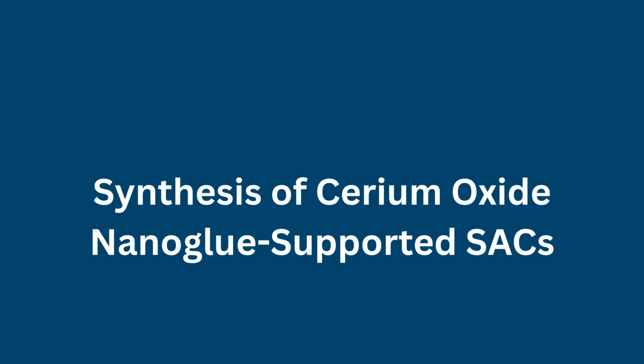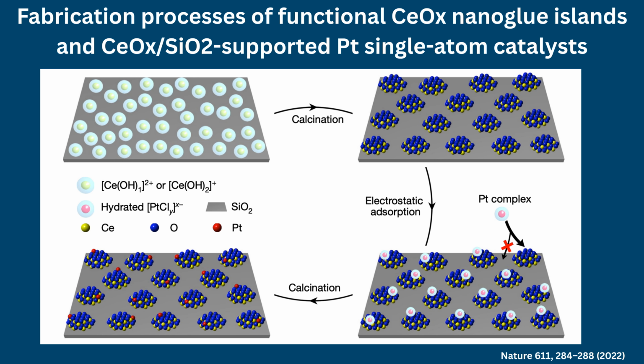Synthesis of cerium oxide nanoglue-supported SACs. The synthesis involves a scalable aqueous phase method based on strong electrostatic adsorption. Negatively charged SiO2 surfaces are functionalized with positively charged cerium hydroxide species. Thermal treatment, calcination, converts these species into isolated cerium oxide nanoclusters, approximately 2 nanometers.